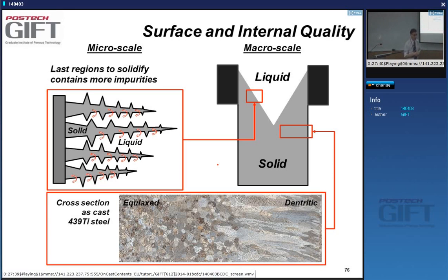when the cooling rates are not too high, you form large crystals, which we call dendrites. During the solidification of these dendrites, we get partitioning. Certain elements will enrich in the solid, other elements will partition to the liquid. So we get two things: dendritic microstructures, and compositional differences. The center here doesn't have the same composition as on the side. But by mixing the liquid while it solidifies, we can minimize this.